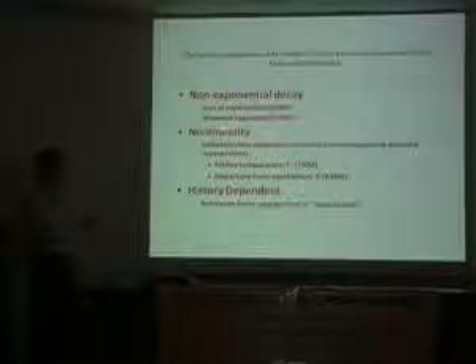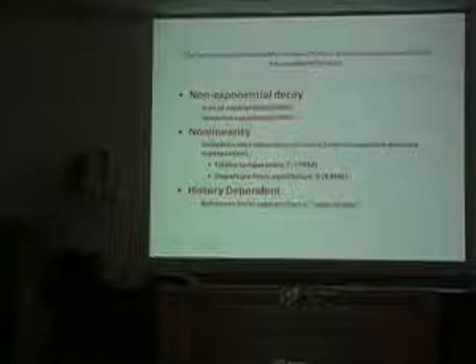So the non-exponential decay, that's what I showed you from both the memory effect and the intrinsic isotherms. The KAHR model uses a sum of exponentials. The TNM model uses a stretched exponential. The nonlinearity is that the relaxation time depends on structure through what we call time, temperature, structure superposition. So that means that the times themselves depend on the structure, but not the shape of the relaxation. Okay, that's an assumption in the model. One of the reasons they made that assumption was when Kovacs was doing his work, and the same thing I'm sure was true of Narayanaswamy and so on, the computers weren't big enough to even consider a changing shape of the spectrum. But it turns out it's a pretty good approximation.